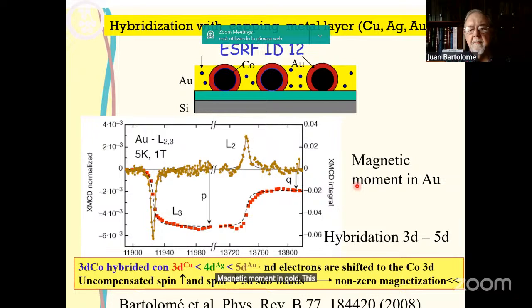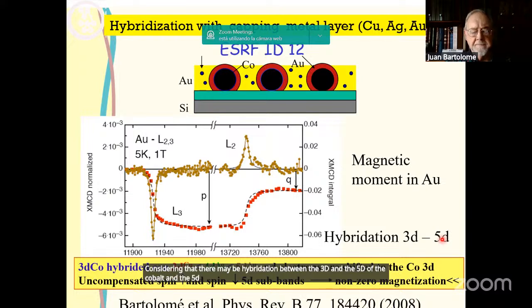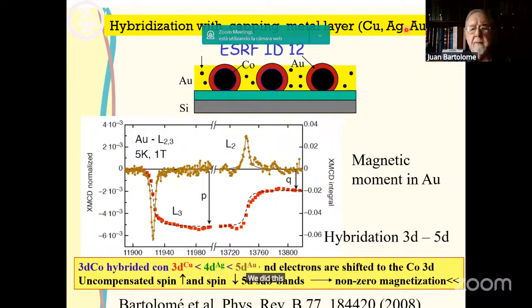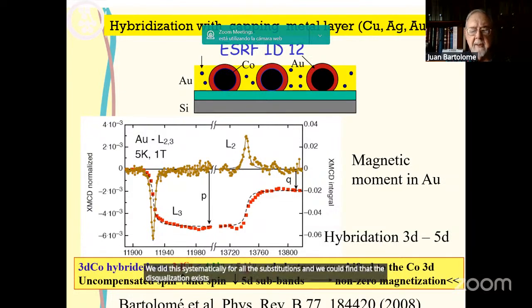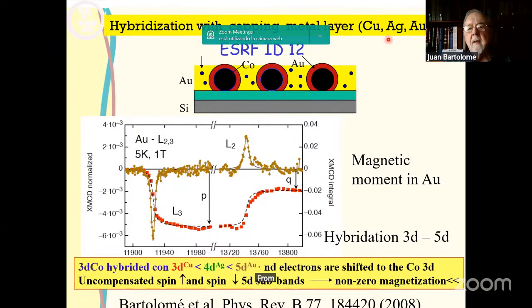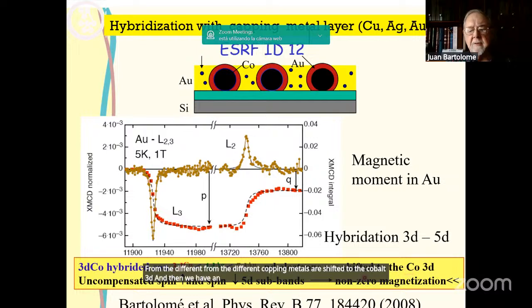This could be understood considering that there may be hybridization between the 3d of the cobalt and the 5d band in gold. We did this systematically for all the substitutions, and we found that this hybridization exists in all cases, and it can be seen that they go in the trend of copper 3d, silver 4d, gold 5d. So the d electrons from the different capping metals are shifted to the cobalt 3d, and then we have an uncompensation between the spin up and spin down 5d subbands, which gives rise to the non-zero magnetization at the capping shell. Okay.